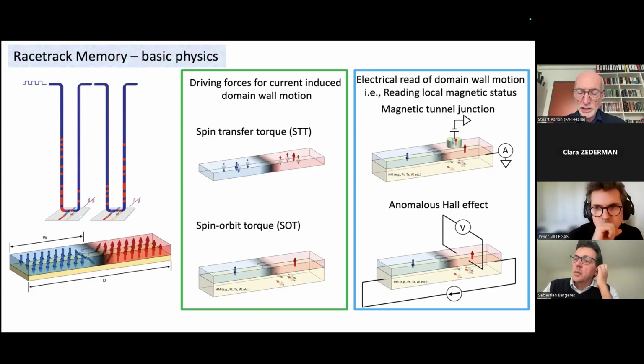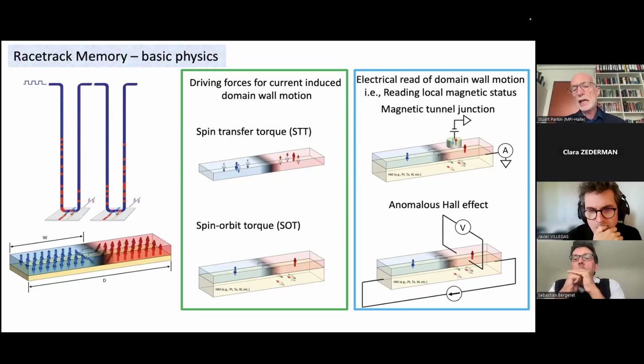So the concept then is that spin polarized electrons, which are generated by this conversion of charge to spin current within this layer, can then diffuse into the neighboring magnetic layer, forming the racetrack, and then it will impose a torque through the transfer again of spin angular momentum. It's called spin orbit torque because typically the yellow layer will have a large spin orbit coupling to generate these spin currents.